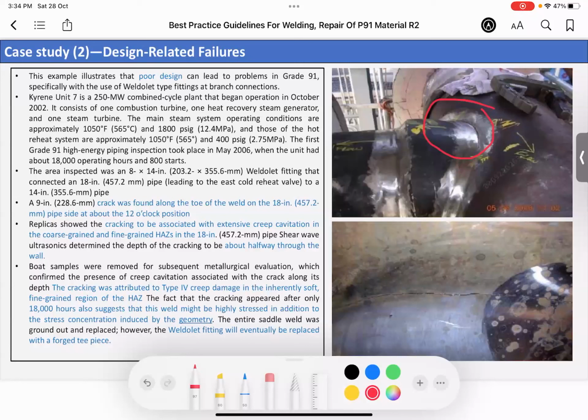So the cracking was attributed to type 4 creep damage in the inherently soft fine-grained region of the heat-affected zone, and it occurred after 18,000 hours. This also suggests that this weld might be highly stressed in addition to the stress concentration induced by the geometry. So the weldolet fitting was eventually replaced with a forged T piece.